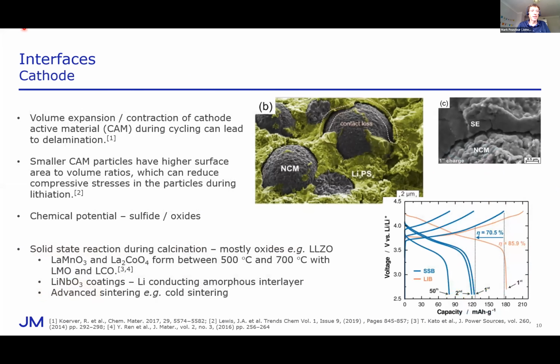So I'm going to finish off with the cathode. I mentioned the cathode earlier on. Volume expansion and contraction during electrochemical cycling of your active material, in this case a nickel cobalt manganese oxide, is really important to deal with. These can expand and contract by up to 8% depending on depth of discharge. If they're bathed in a liquid, it's not a problem. However, in an all solid state cell, in this case the electrolyte is this lithium thiophosphate, the contraction during delithiation results in delamination of the active material from the electrolyte, and once that's cut off, it's electrochemically isolated, and so you lose the capacity of that material.